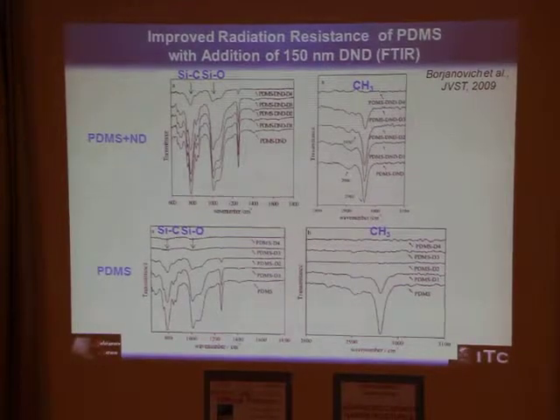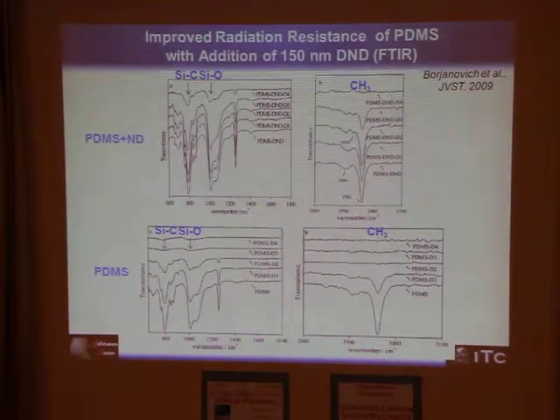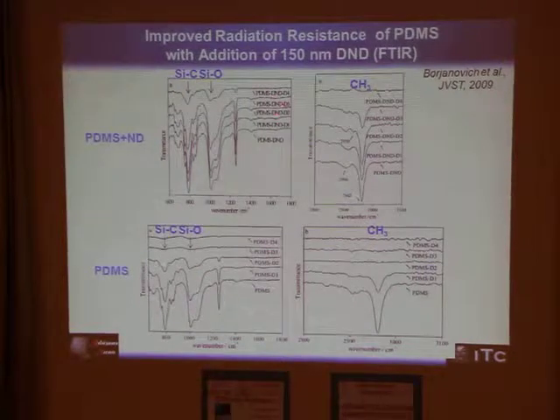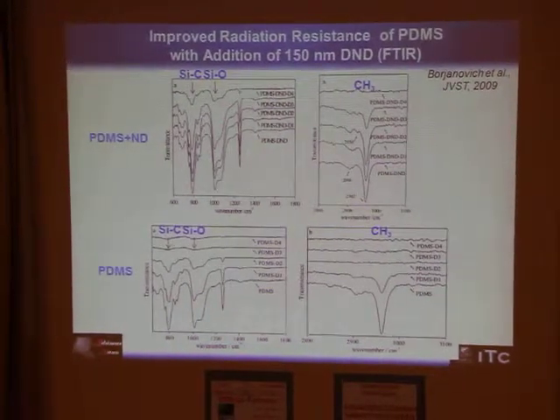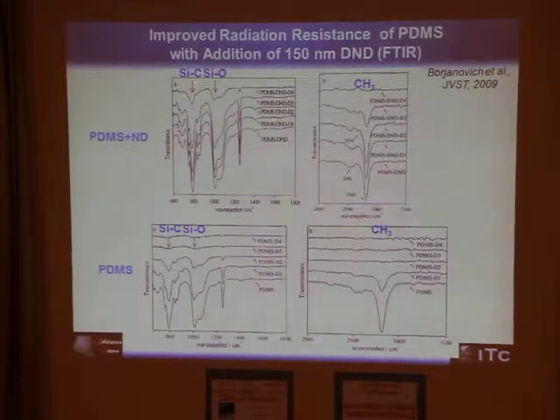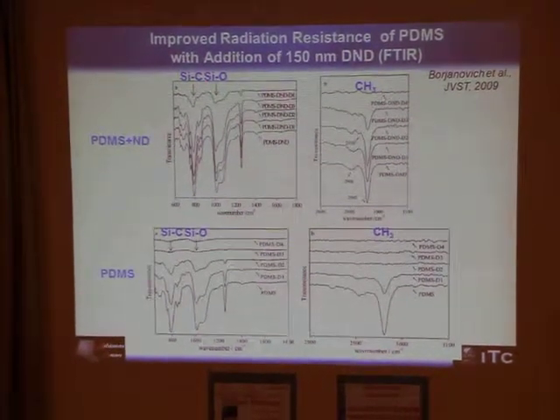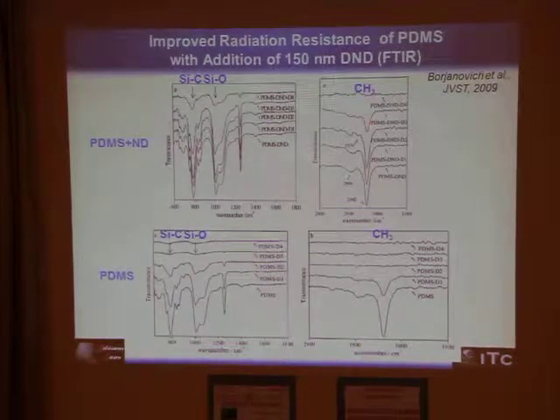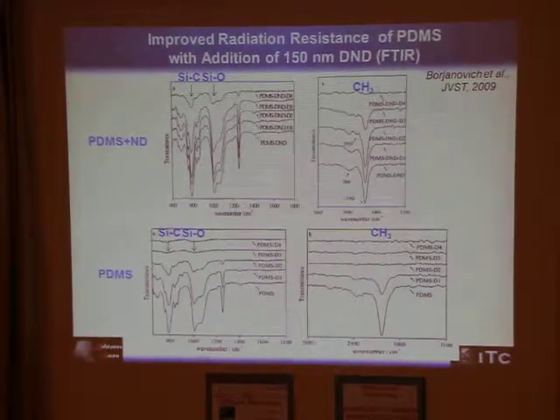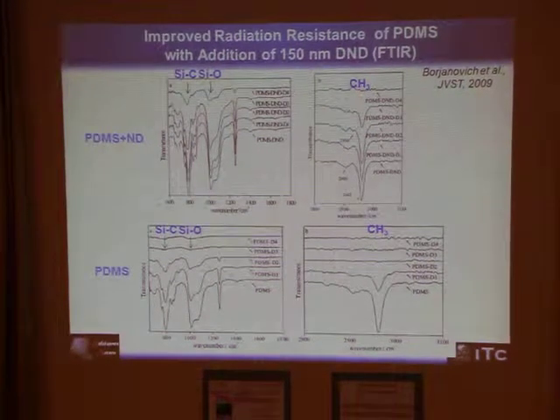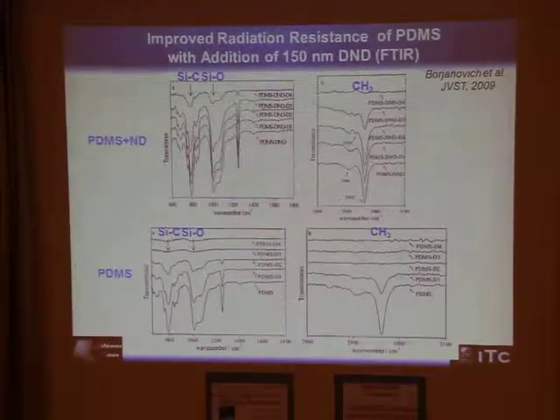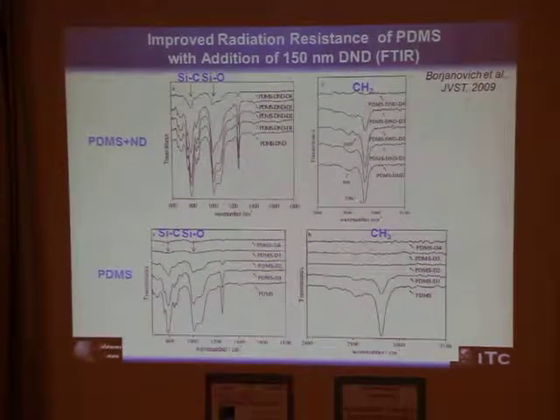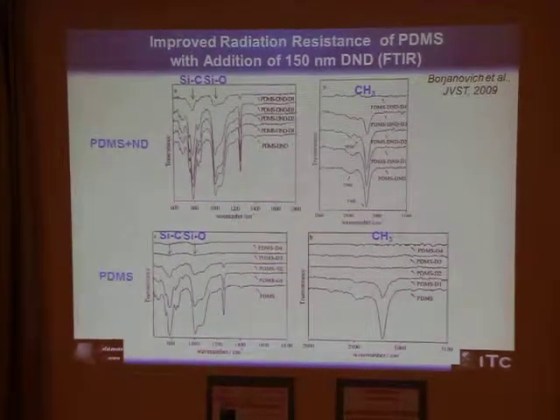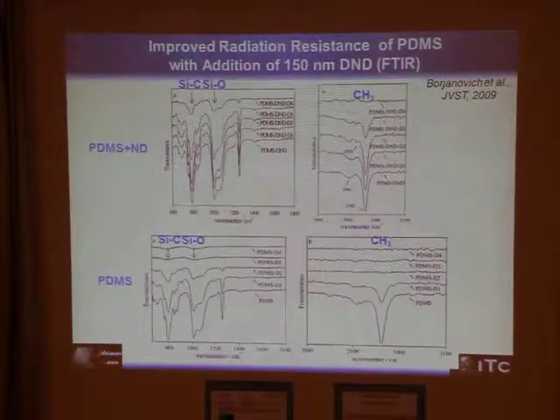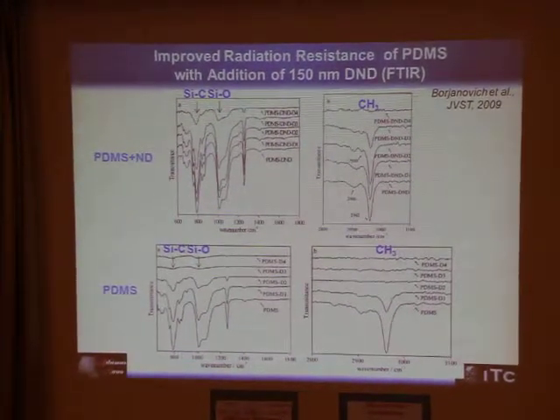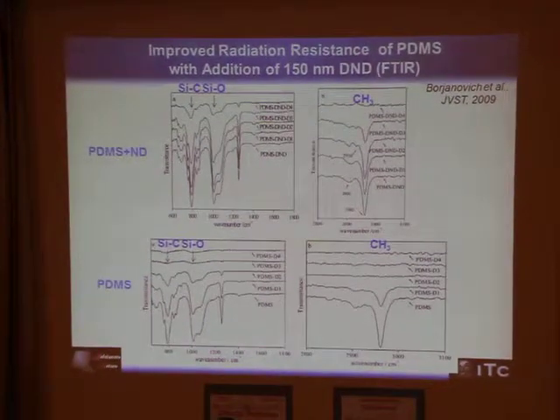And what happens in the presence of nanodiamond? Quite interesting things happen. You can see that at D3 all characteristic peaks are still present for both the backbone chain and side chain, as well as the CH3 group, and hydrogen is stripped out only at the highest dose, while features for CC and CO are still present. So we conclude that the presence of nanodiamond in the PDMS matrix provides enhanced radiation resistance.